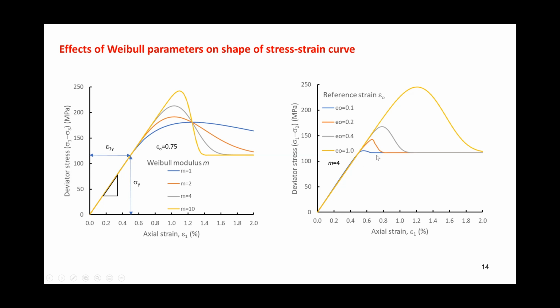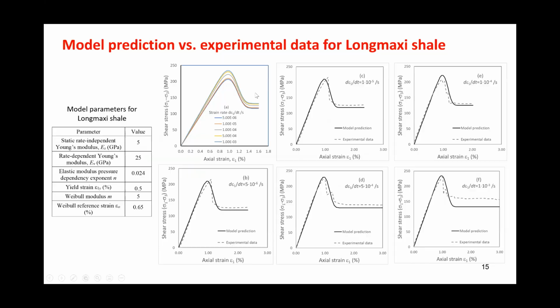The reference strain also has a similar effect. Increasing epsilon_0 increases the shear stress, the peak value, and also the axial strain corresponding to the peak. So both the peak increases and the stress-strain curve moves to the right before they drop and go to residual.